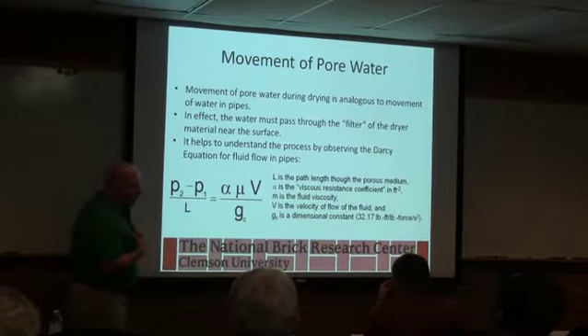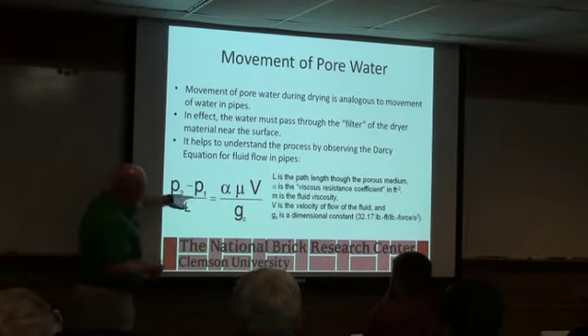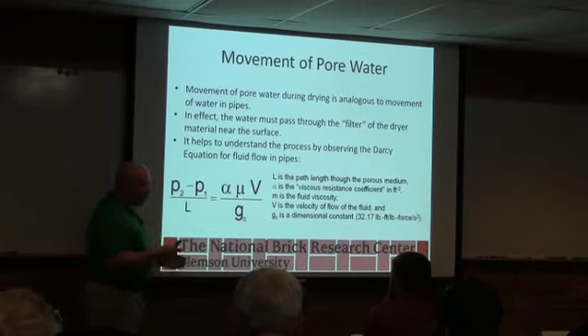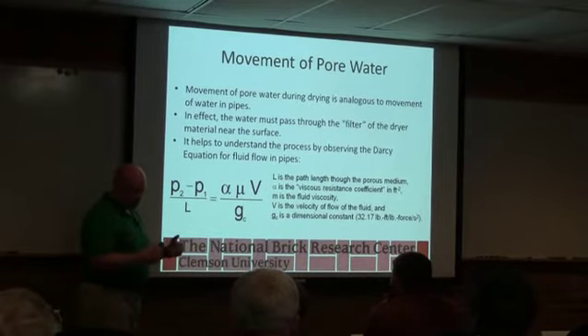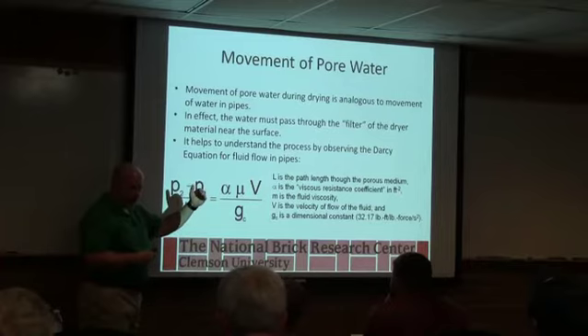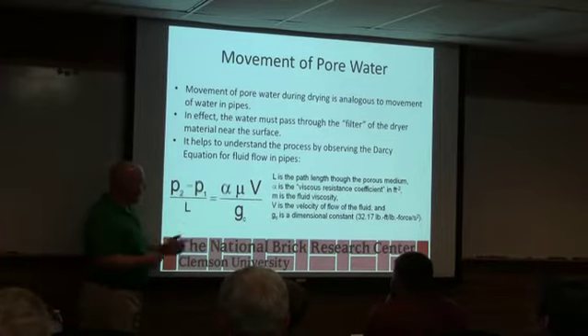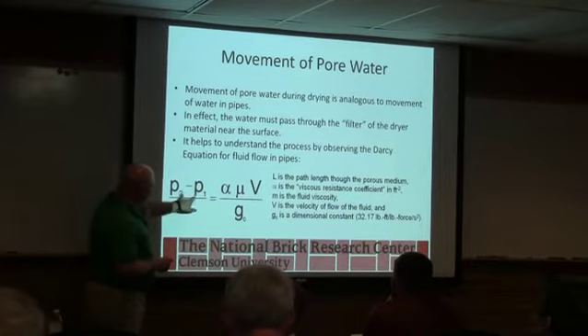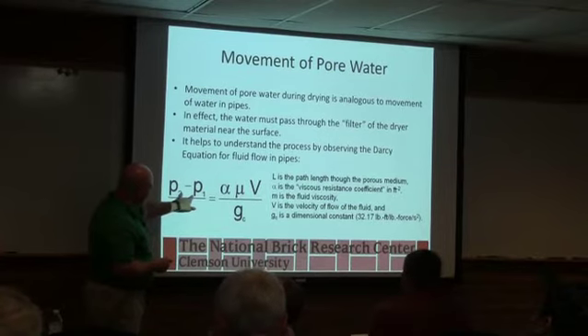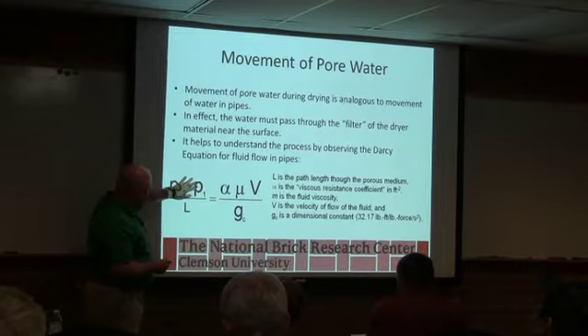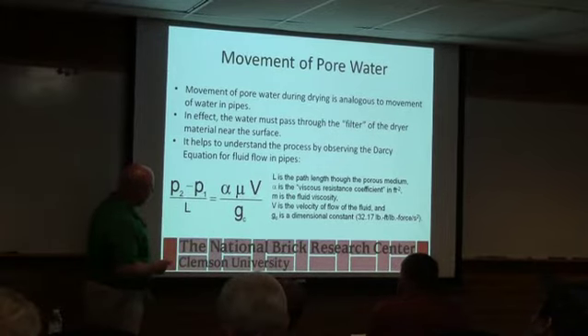We're creating that driving force, and you can think of that as a driving force, by the humidity differential between the inside of the brick and the air in the dryer. Okay, so we're manipulating the air in the dryer to cause a driving force. Initially, in the beginning of drying, we want this to be pretty minimal so that we're controlling the drying rate, and as we go further and further in the dryer, we're making that difference bigger, so we're forcing drying.